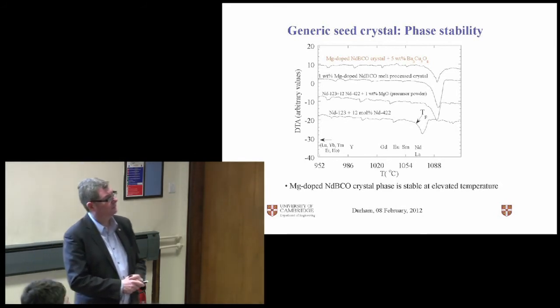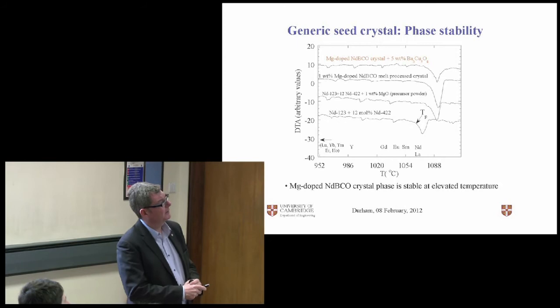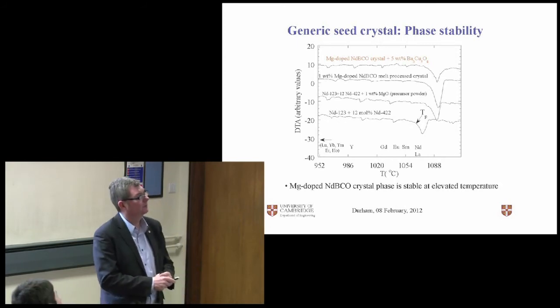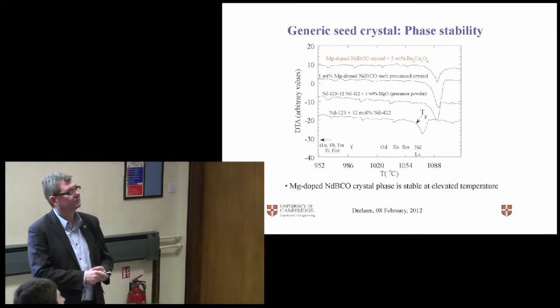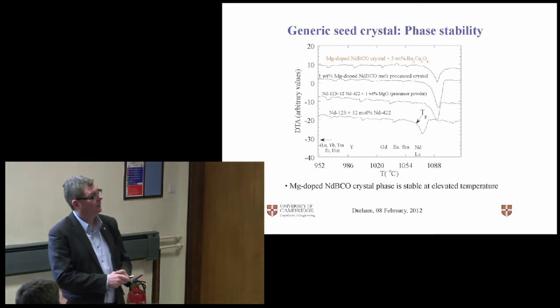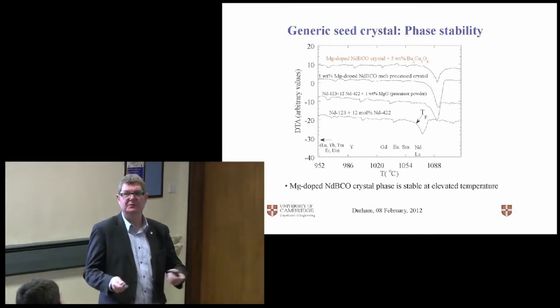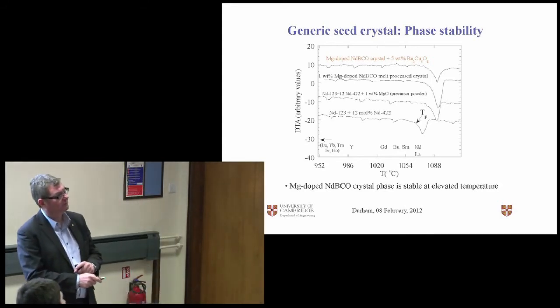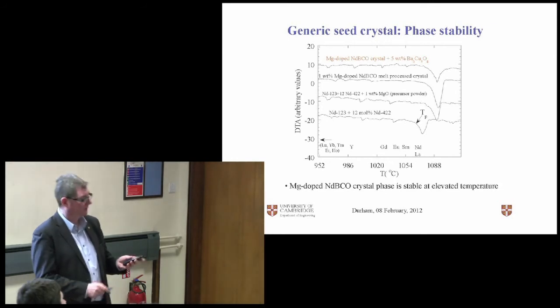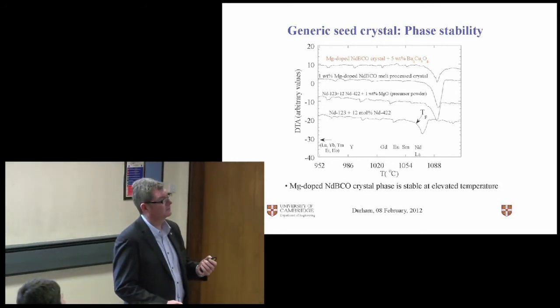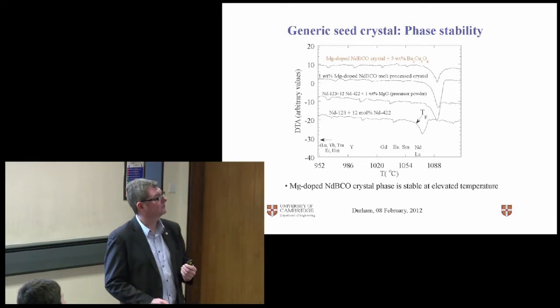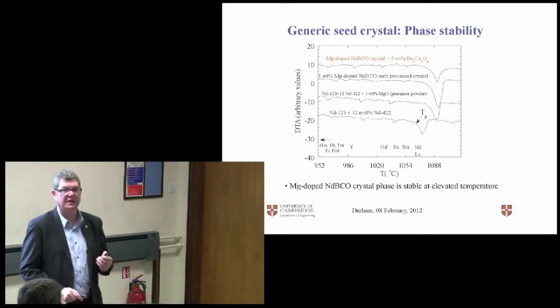And then finally, and most searchingly, we take our magnesium doped neodymium barium copper oxide crystal and we add to it some very corrosive liquid, a liquid that would be formed at high temperature in a melt growth process, and we still see this high decomposition temperature. So this shows you that the seed has got the right structural characteristic, it doesn't react, and it's stable at high temperature.